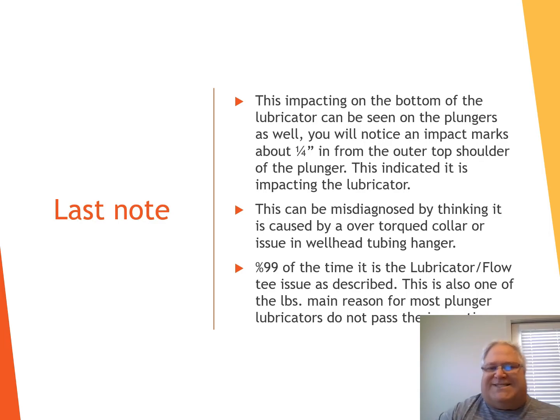And sometimes that's mistakenly credited to tight collars or going through the wellhead, like the hanger or something. But most times that's not the case. Most times it's going to be a result of it hitting the bottom of the lubricator. So if you see this when you pull plungers out, it's a good idea to pull that lubricator out and inspect it to see what kind of damage is happening to that lubricator itself.